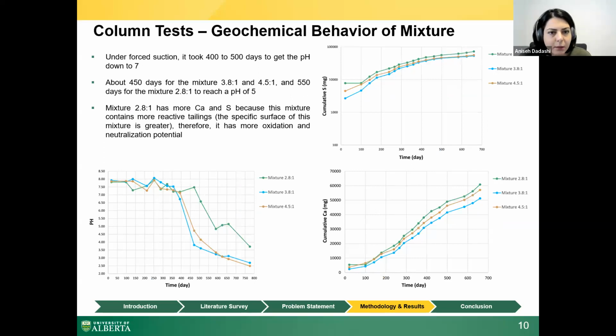These are some of the results of the water quality test for the mixture columns. As you can see here, under forced suction, it took 400 to 500 days for mixture material to get the pH down to 7. If you remember, the tailing control column became acidic after about 300 days. For the ideal mixture ratio and partially filled conditions, shown in blue and orange in the graph, it took about 450 days to reach a pH below 5.